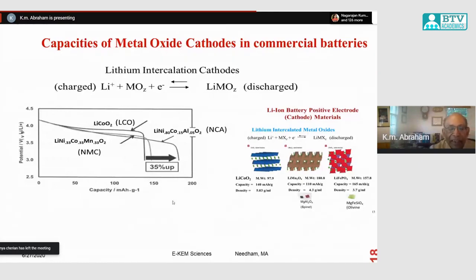Lithium cobalt oxide. Now, cobalt is an expensive material, and it is also rare. It's mostly produced in some countries in Africa. They are always fighting there. So there has been a lot of work to replace the cobalt in the cobalt oxide. That is done by substituting some of the cobalt with manganese and nickel. So these materials, nickel, cobalt, manganese, have the same structure as cobalt oxide. However, you have much less cobalt.